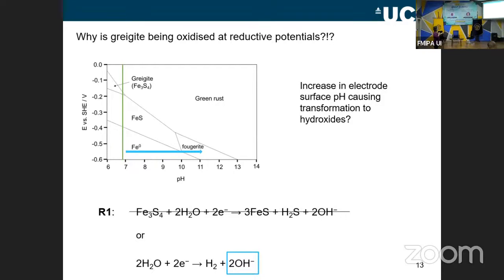So the reduction of water going to hydrogen, and importantly, this reaction produces hydroxide right at the surface of the electrode. Now we are using a buffer solution, which should be able to buffer the pH. But if we're producing a lot of hydroxide, it might not be able to buffer it quickly enough. And if that happens, the pH would move from 6.8, where it starts, all of the way into this region here. And all of a sudden, we're in the region where the rust, the hydroxide, the oxides, and this species fougerite, which is oxide or hydroxide species, are stable.